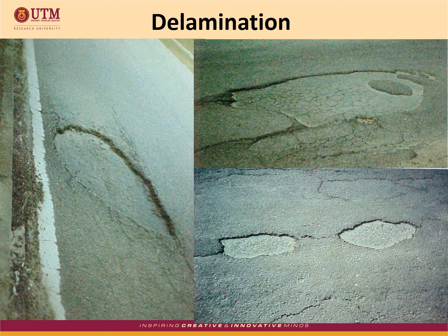Okay, this slide shows us the delamination problem, which refers to the separation of the top wearing layer from the layer underneath due to poor bonding of the two layers. The causes of delamination can be a lack of tack coat between the two layers and also seepage of water through the surface layer. Therefore, strong bonding between the two layers should be ensured before laying the wearing course or the overlay, by providing enough coating with a good quality of bitumen selection.